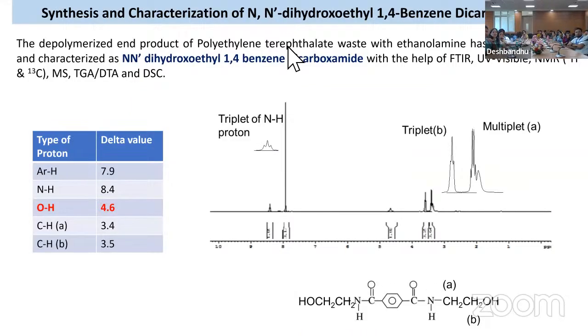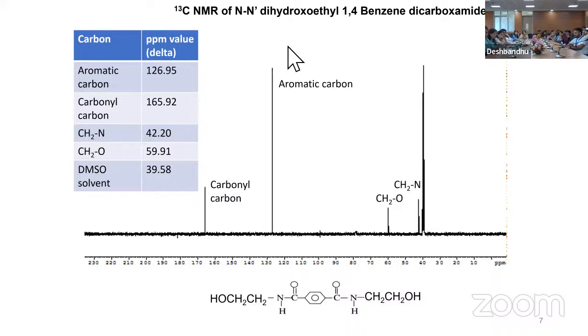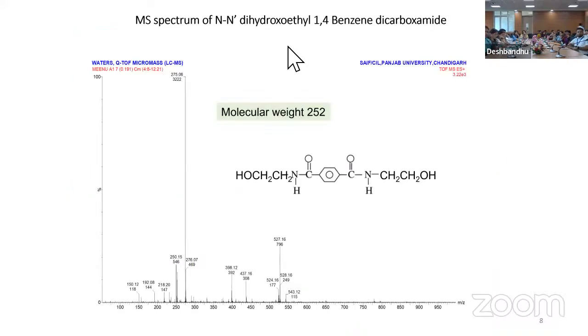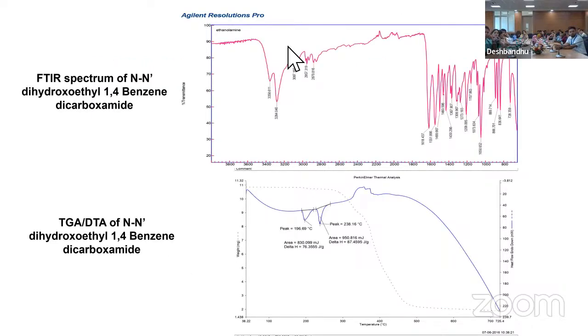So we have synthesized this monomer at ambient conditions of temperature and pressure with ethanolamine. After depolymerization, we get this. We have characterized this through FTIR, UV visible, proton NMR, 13C NMR, MS, TGA, DTA, and DSC. This is the data tabulated here, and we can see all the peaks are at the right positions for all the protons. In 13C NMR too, this monomer is well characterized, and this is the MS spectrum. Molecular weight is 252. Then FTIR spectrum, then TGA, DTA for melting point.